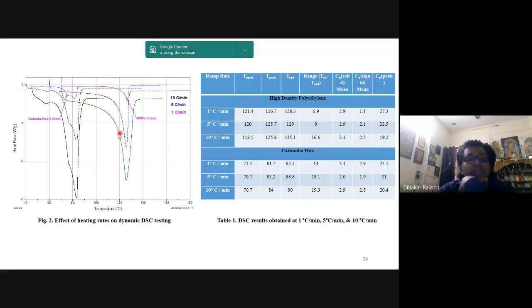In that study we have taken two phase change materials: carnauba wax and high density polyethylene. We attempted to utilize both of them in cascaded form. The structure I will be showing. Again we have done the thermal characterization utilizing these two phase change materials at different ramp rates. Of course, ramp rate is also important, that is, the rate at which you are giving the heat, or the rate at which the temperature of that particular phase change material is changing.